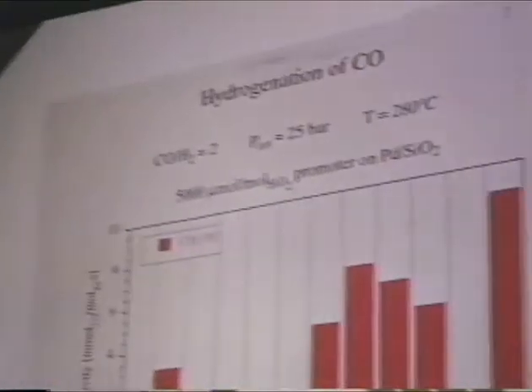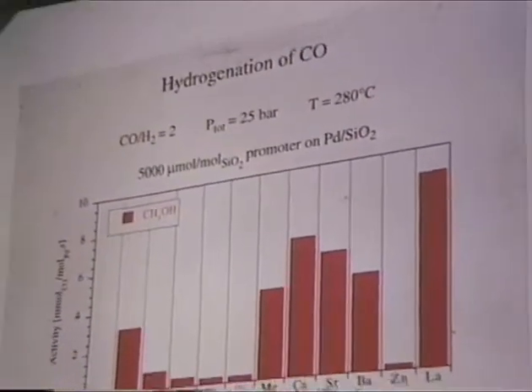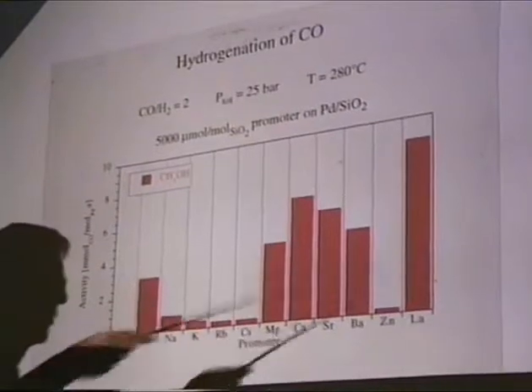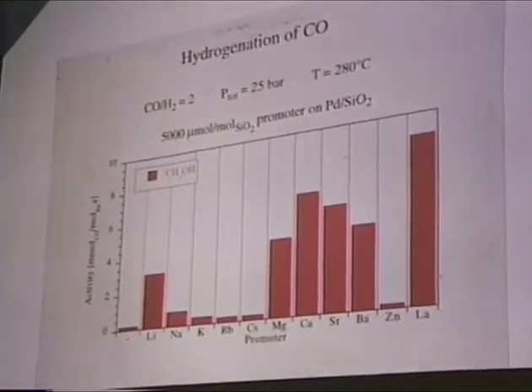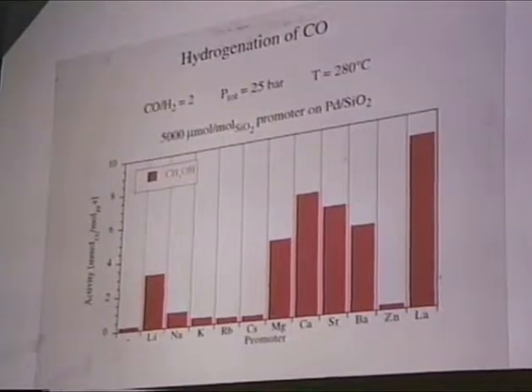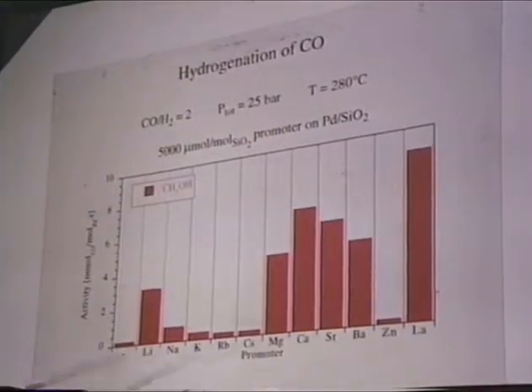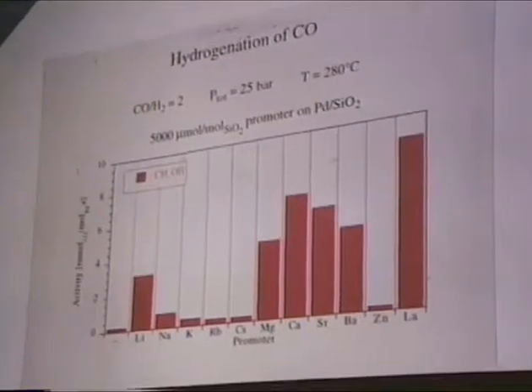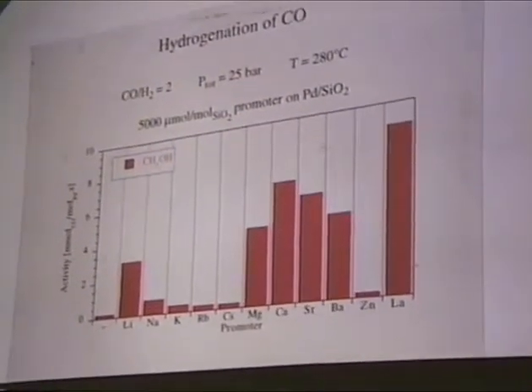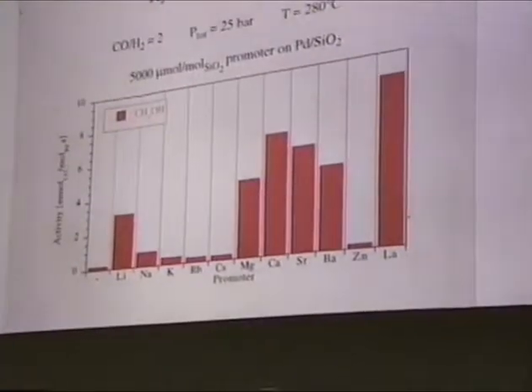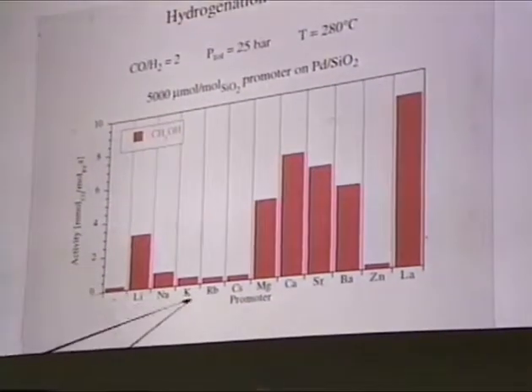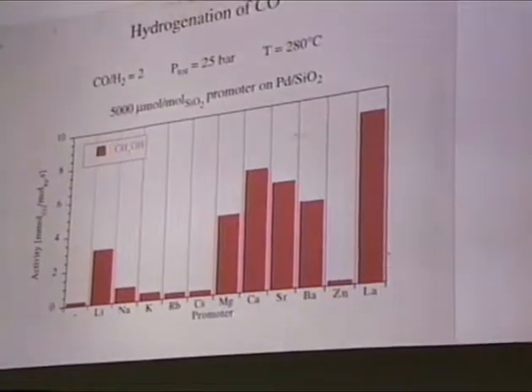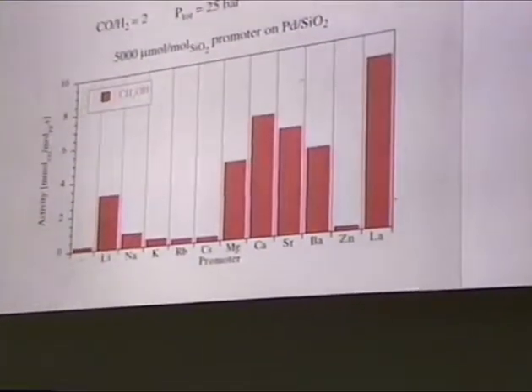So we studied several other promoters. And here's a whole series. The alkali metals and the alkaline earth metals and one or two others. And you can see that it's not only the calcium which is doing a good job, but the lithium is quite good, and then you go down. This was already seen by Professor Tamaru in 1981. He had a publication in Transactions of the Faraday Society where he started with the lithium, sodium, and so on salts of the palladate, and where he showed the same trend.